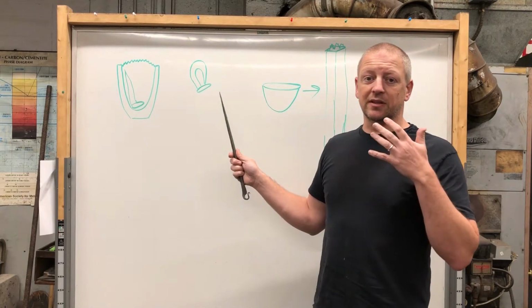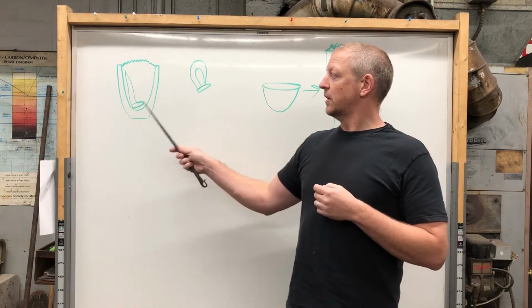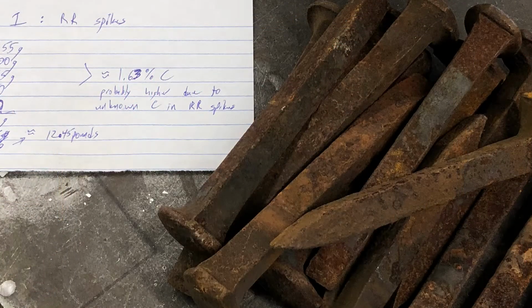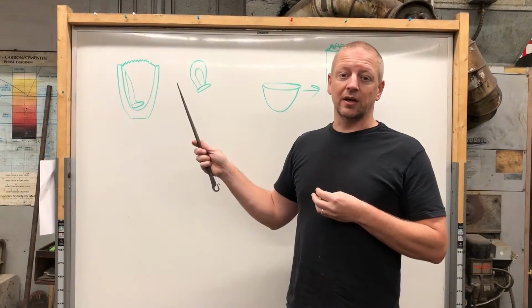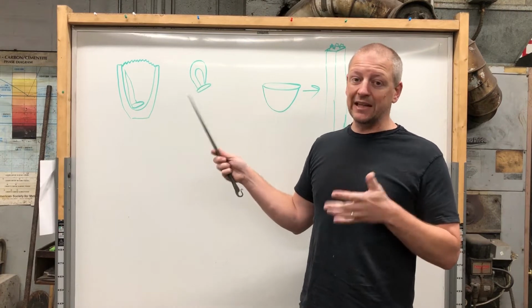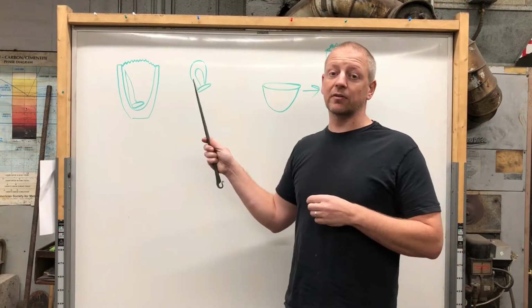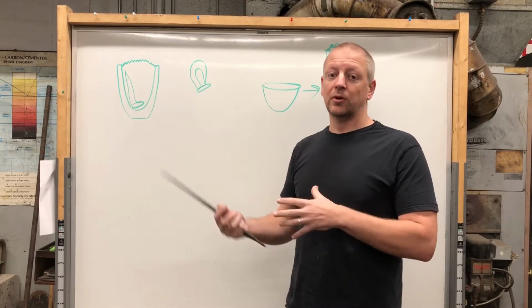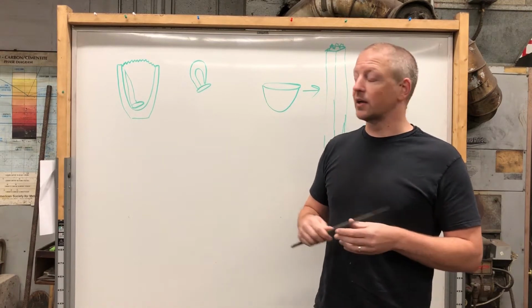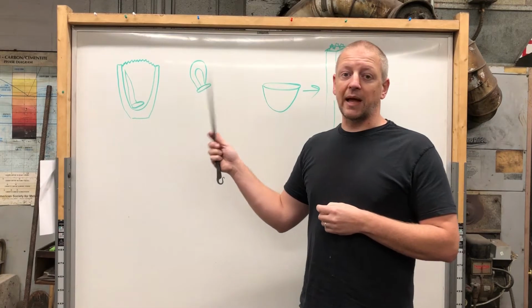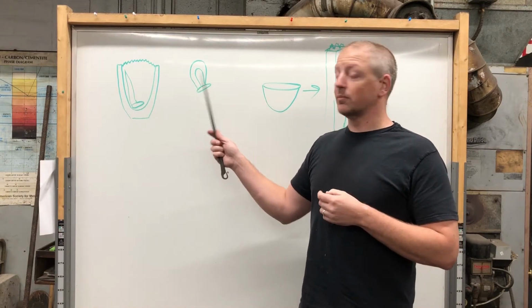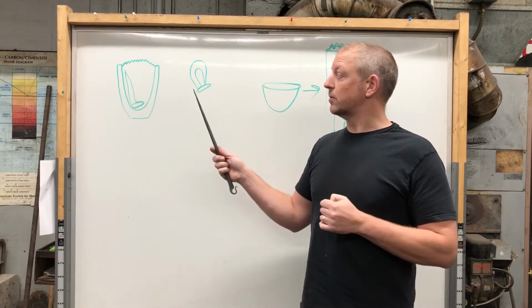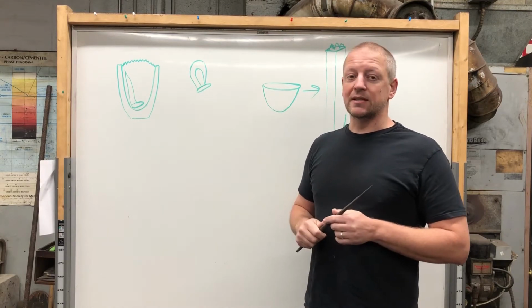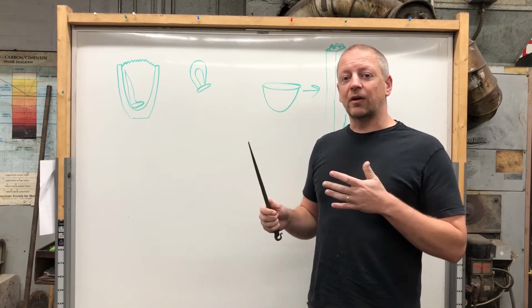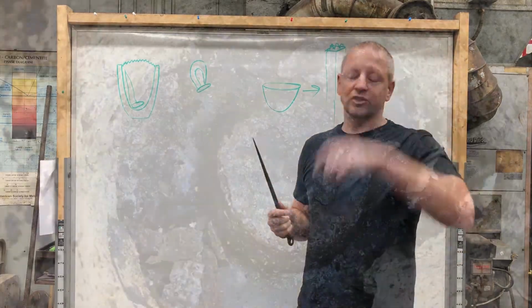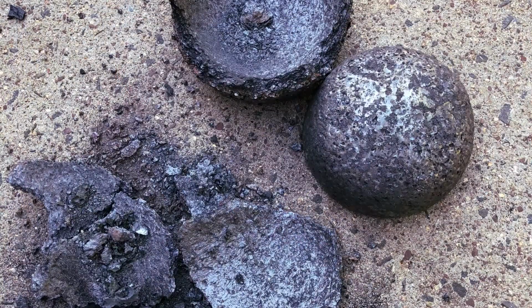And that actually has a second good effect. These were all super rusty. I didn't clean them off. The bending process, and the heat especially that's involved in that, converts a lot of the oxide from red oxide to a black oxide. And that black oxide is a little easier to deal with. Plus, a lot of it just flakes right off. So, like I said, that's something I should have dealt with right at the beginning. I charged ahead and it bit me in the butt.